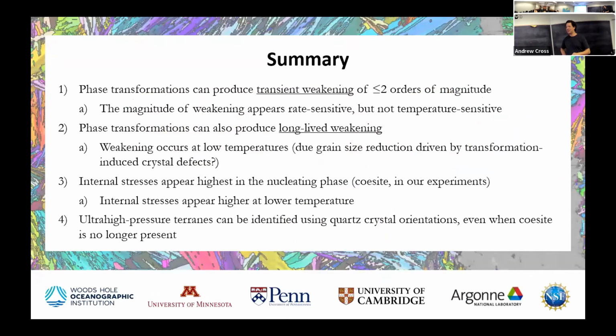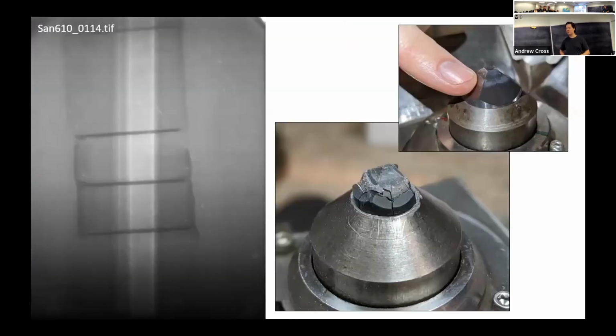So we can get transient weakening. We also see long-lived weakening. Internal stresses are highest in the nucleating phase, and we can use quartz crystal orientations to tell whether something's been to ultra high pressure conditions.